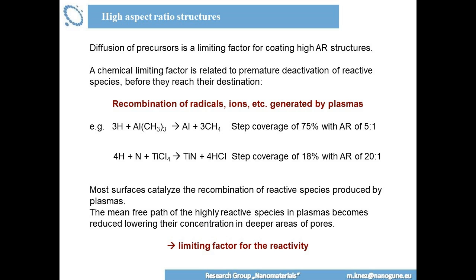Chemistry is an important point which needs to be considered. Think about your chemistry which you are using. Think about the radicals and plasmas which you use. And many of them, if they are really short-living, you will not be able to get into deep pores. So the conformality in high aspect ratio structures will be very poor in that case. But if your chemistry is okay, then you need to think further.